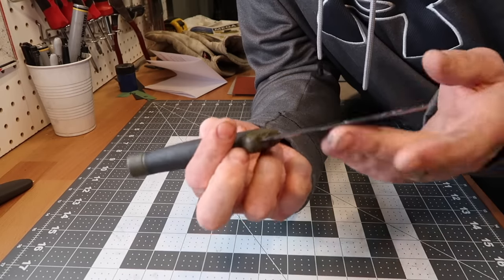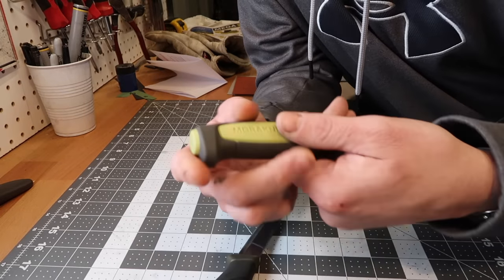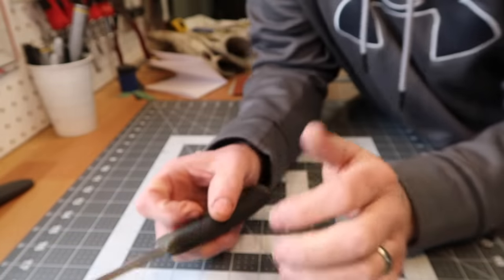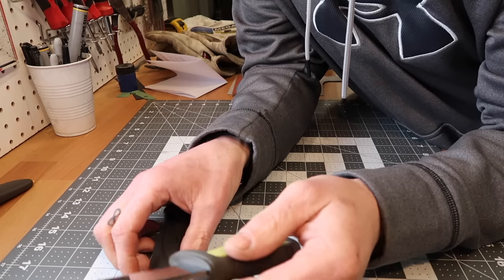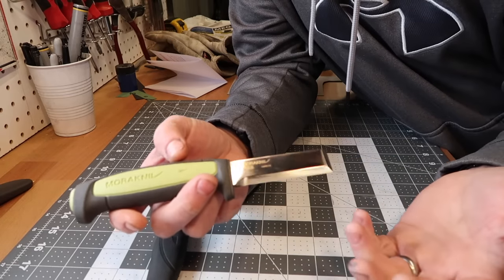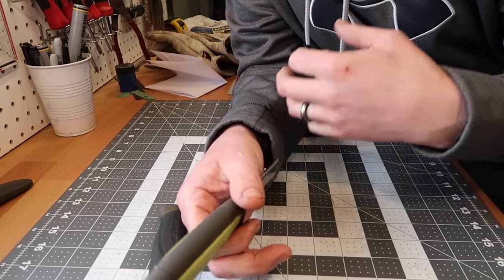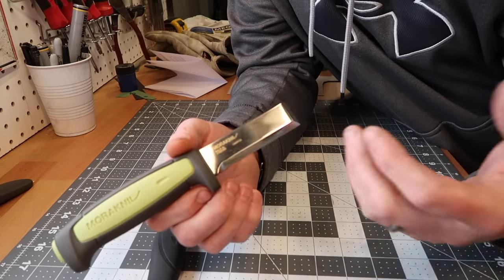These are made in a factory — all these blades are probably stamped, clamped in a machine and ground. They come out really well and hold their edge well, even the stainless one. They don't give any specs on the steel — this one just says 'carbon' but doesn't tell you the type of carbon or steel, and the Companion just says 'stainless' without specifying the type. In the last 10 or 15 years, stainless technology has come a long ways. It used to be that if you wanted great edge retention you needed carbon. One of the better stainless steels you could get was 440, which by today's standards is very bottom-end. I've got some 154CM which is a little better, and CPM 154 which is really good, but the heat treatment process on those is so much more work than a 1095, 1085, or O1 tool steel.